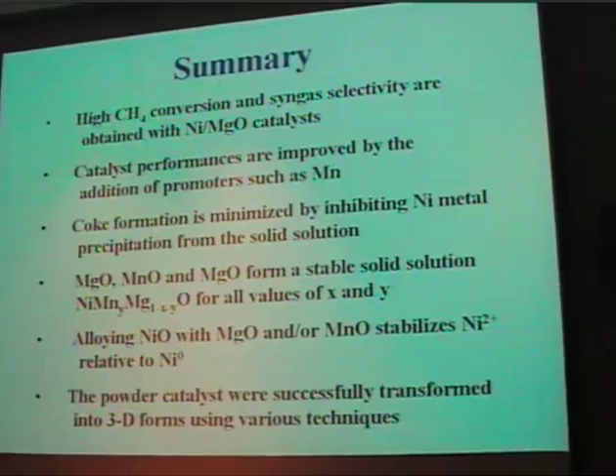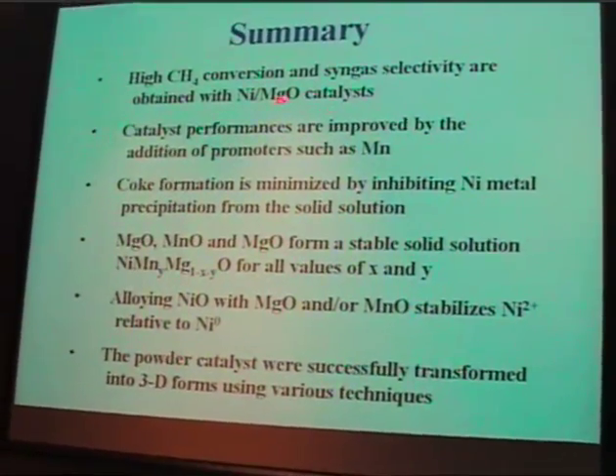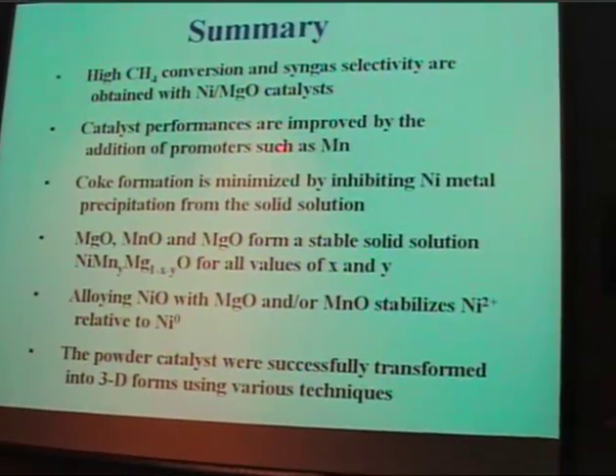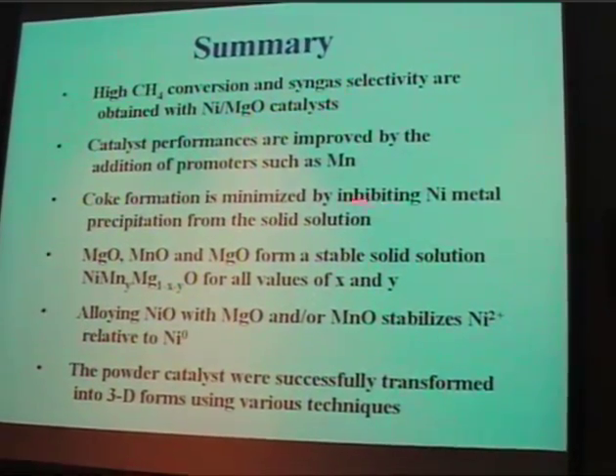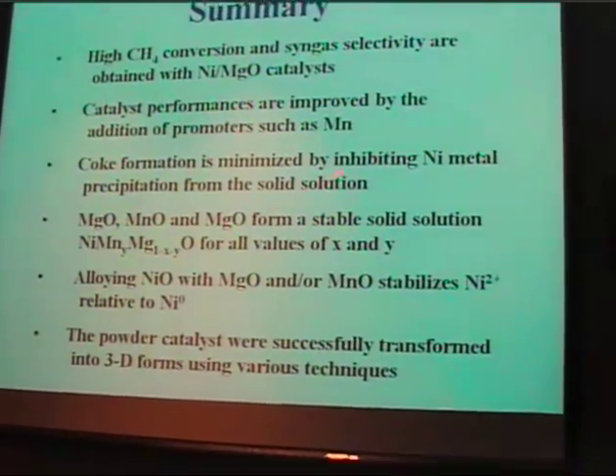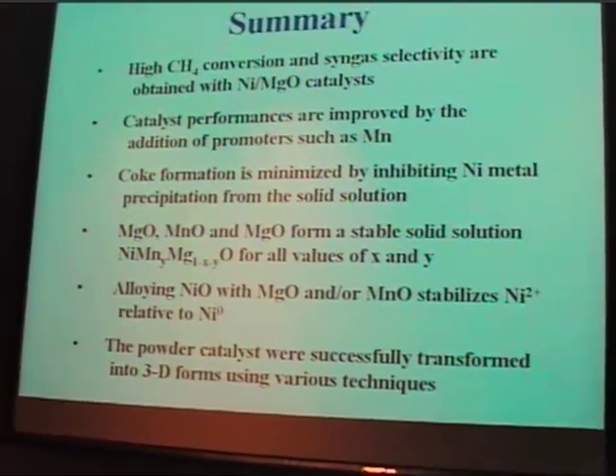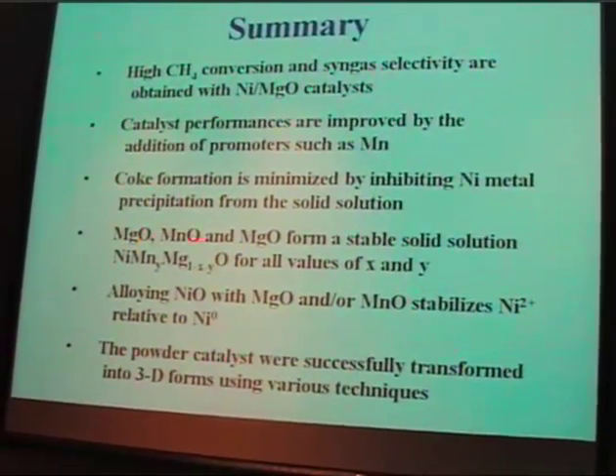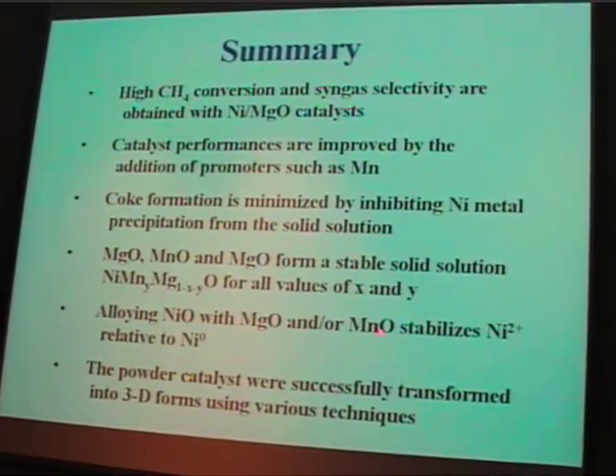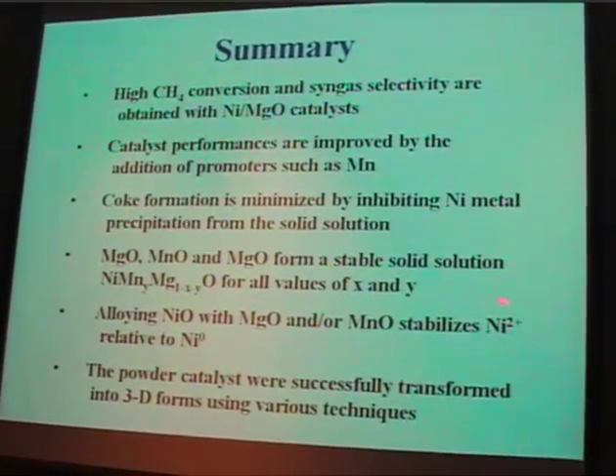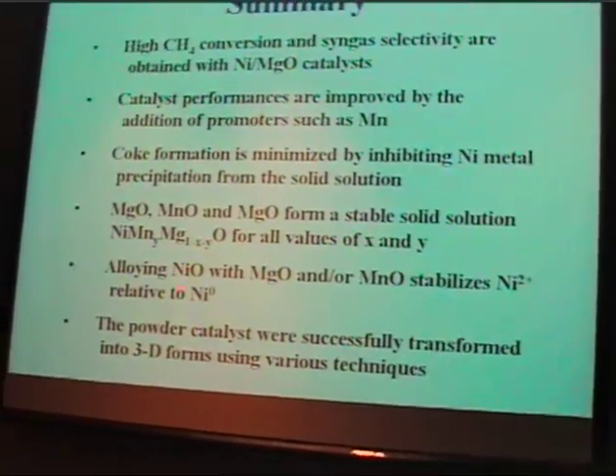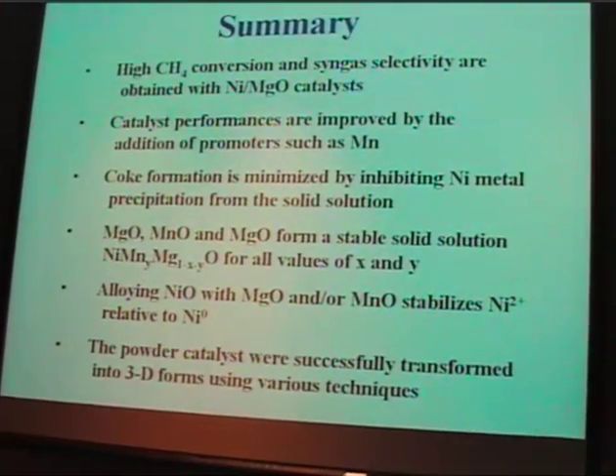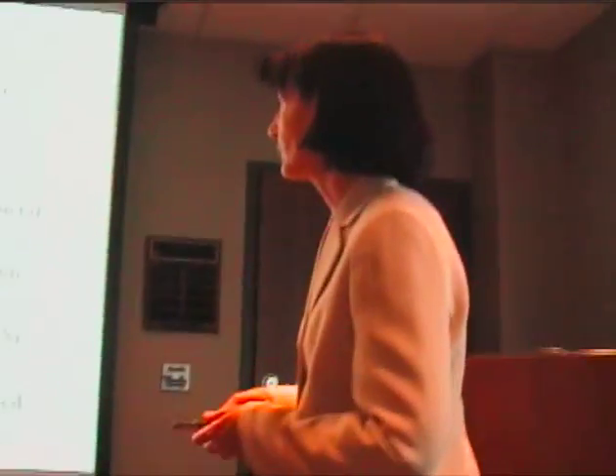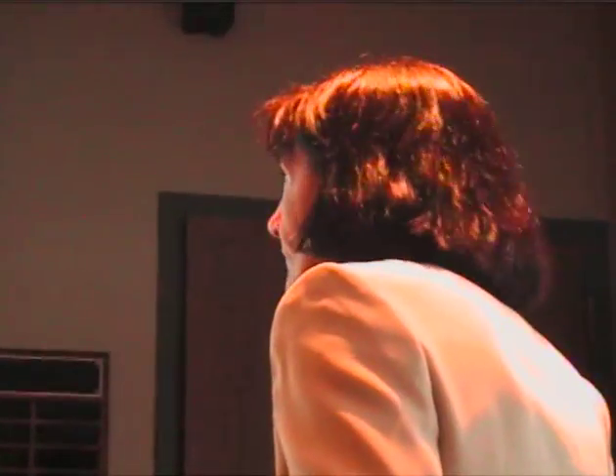So in summary, we've been able to achieve our target conversion and selectivities with a nickel MgO, and then adding the promoter in there, we get improved performance, as you saw. The coke formation was minimized, saw very little precipitation. Be interesting to go back and understand that mechanism further. All the components are in a solid solution, and definitely alloying the manganese in with the nickel and the MgO helps to stabilize the nickel in the +2 oxidation state, which is to our benefit. And then basically being able to take the powdered catalyst, transform it over to a 3D structure, which would be necessary to move on to the next phase.